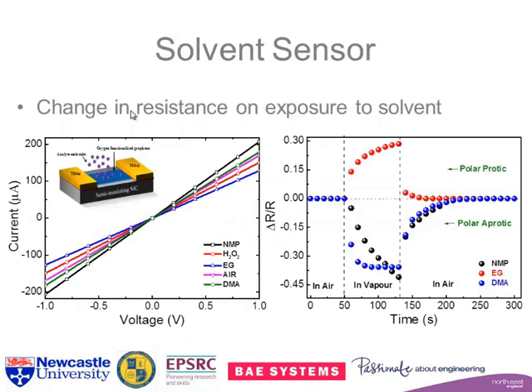So in terms of solvent sensor, here's our device. We expose it to analytes at about 0.1% in standard laboratory air in Newcastle. Air is the pink line, and we get either an enhancement in current or a decrement in current, depending on which type of solvent we put on it. And we generally show them then as delta R over R. Two things, polar protic material, so these are hydrogen donors. We get a response, then when we remove it, it goes back to 0.